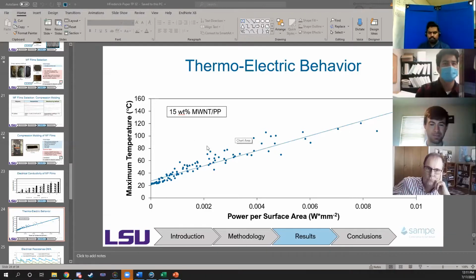Right, so let me see if I can pull up the relevant thing. I'll share the relevant graph that I was talking about. It was this figure here. And for this weight fraction of nanotube polypropylene, the R-squared was 0.9039, so a fairly good fit for a linear fit. We also studied 2 other weight fractions of nanotubes and polypropylene, 20% and 25%. The 20% had an R-squared linear fit of 0.89, and the 25 weight percent had the lowest R-squared of 0.83.